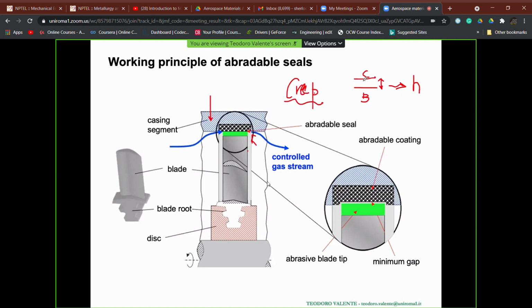But at the same time, we cannot use, without any other solution, a gap which is just calculated on the basis of the maximum elongation, maximum deformation, which is requested to be tolerated for, for example, 10,000 hours of lifetime of our engine, because it would be so high that the gas coming from the combustion chamber will not interact with the profile of the blade, but will skip through this conduct, and thus we will not have any possibility to generate mechanical power. And so what is done?